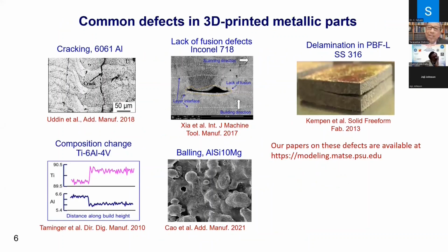A selected few are shown here. The most prominent problem is cracking, solidification cracking, if you will, but also other forms of cracking, lack of fusion defects, residual stress, distortion, in extreme cases delamination, as shown here, composition change, because alloying elements sometimes contain volatile components, and they are selectively vaporized so that the composition of the part can be different from the composition of the feedstock material, and surface roughness.